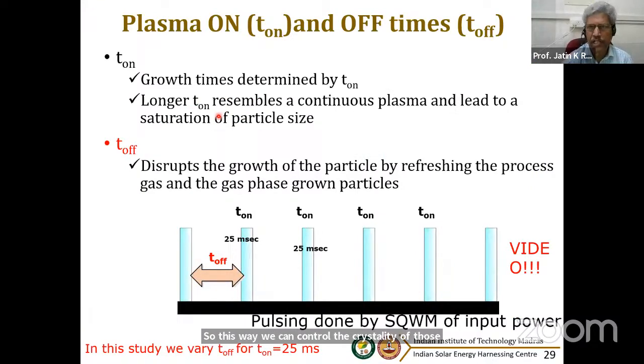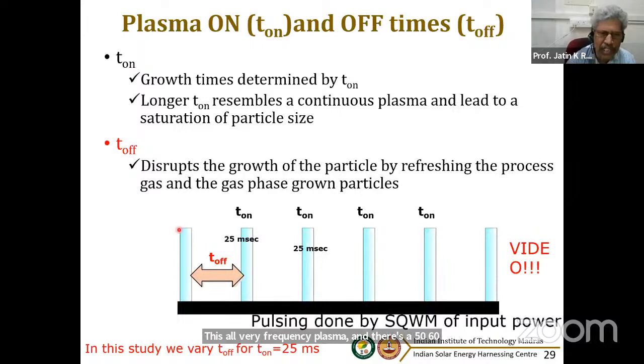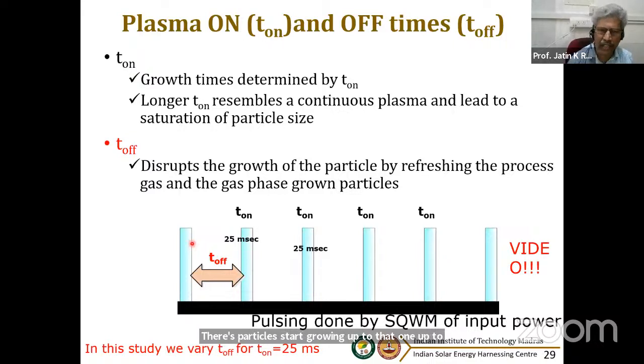The second method that is used is called pulsed plasma. You pulse the plasma. That means you don't have one continuous plasma. This is all very high frequency plasma, 50, 60 megahertz. But you pulse it. Pulse means you are on for some time, then off, then on, off. This on time will tell you the growth of the particle. The particle will start growing up to that point, and after that the particle will be collected by the substrate. Then again the plasma is up, then again particle formation starts. So from the on period, you can control the size of the particle. And the off period will allow the particles to get out of the system, and also flushes the chamber.